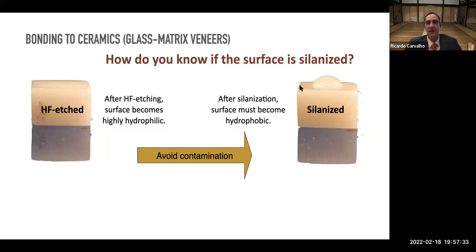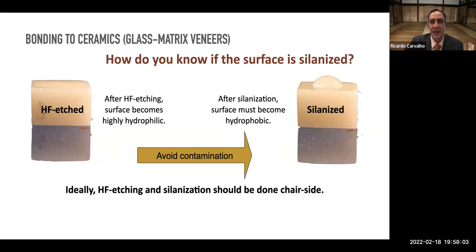And that's the important stage. Avoid contamination from here to there, because after etching, imagine if I place my try-in paste right now, it will spread readily, it will get into the porosity, and all those try-in pastes contain granular color dyes, and those can be entrapped in the surface, and it's hard to remove. So after you etch, you silanize first, and then you do your try-in, you do anything you want to do, because then it's easy to rinse because it is more hydrophobic now.